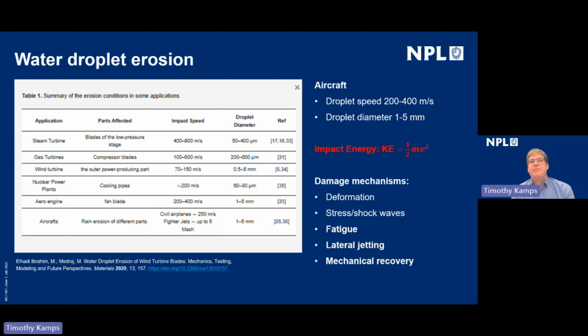And the mechanism of damage of water droplet erosion is laid out on the right-hand side. We've got deformation that's caused by the droplet impacts, stress and shock waves that reflect through the material, resulting in fatigue. And then as the droplet collapses, the water jets out sideways, and it's called lateral jetting. And this can have a big impact on how materials wear if they have surface topography of an order which will interfere with the lateral jetting.